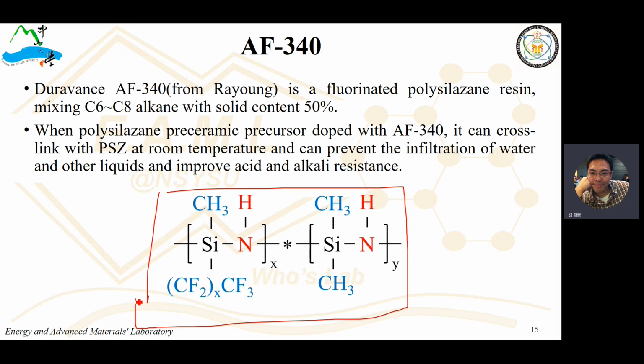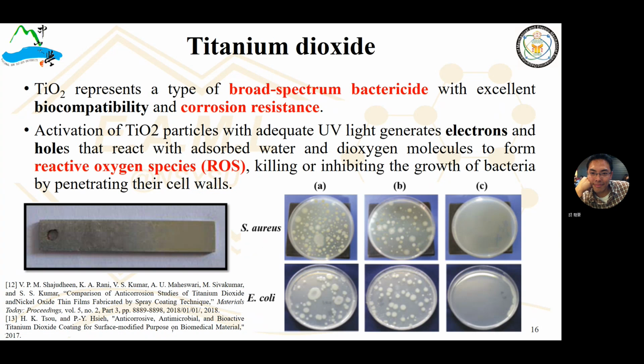Okay, and then when the polysilazane pre-ceramic precursors are incorporated with this AF-340, it can cross-link with the pre-ceramic precursor at room temperature and can prevent the infiltration of water and other liquids and improve the acid resistance, and so on.